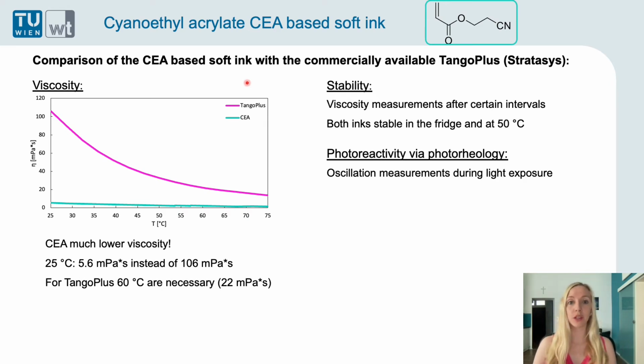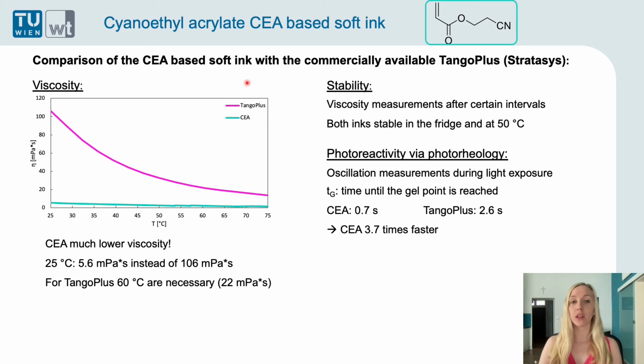for the photoreactivity. One is the TG, this is the time until the gel point is reached. This means the time until the material gets from a liquid state to a solid state, and the cyanoethyl acrylate needs only 0.7 seconds to reach the gel point, while the Tango Plus needs 2.6 seconds. This means here the cyanoethyl acrylate is 3.7 times faster than the Tango Plus.